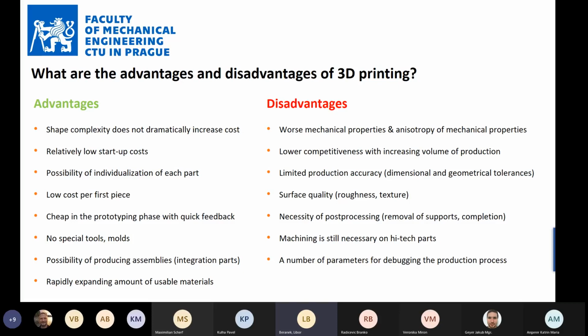Then we have another issue, which is surface quality. And the more productive the additive technology, the worse the surface finish. On the high pressure die casting of aluminum alloys today, you can get a surface roughness somewhere around Ra 5 micrometers, even lower. So quite a nice surface finish. On additive manufacturing, when you use powder bed technology and laser, you are usually somewhere around 15, 20 micrometers, the mean or average roughness. And if you use, for example, electron beam, which is much more productive, much faster, then the surface roughness is like 30 or 40 micrometers, so 2 times worse than using the laser. So it's always some kind of setback.